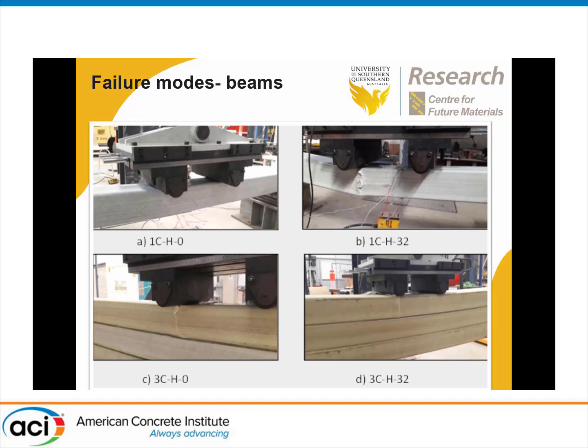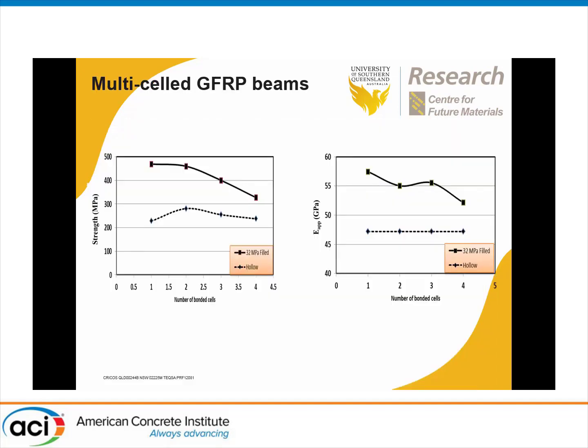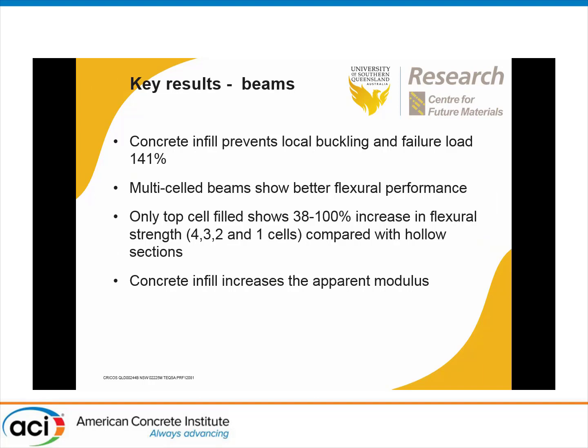So going through these results, what we find is when we increase the number of cells, the strength characteristics with hollow compared to filled concrete change, and as we get more bonded cells, we find the stiffness can be enhanced, and by producing this we can also improve the flexural performance. So this is a beam we could use as a flexural member.